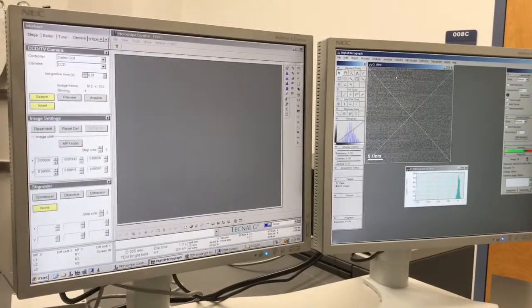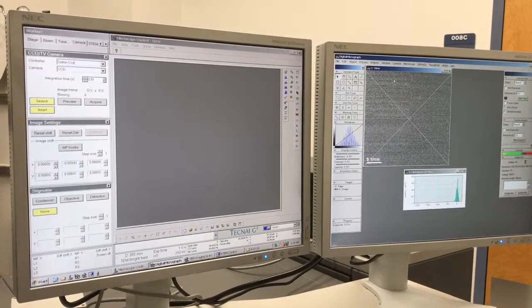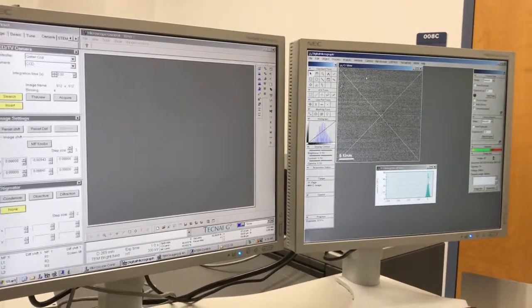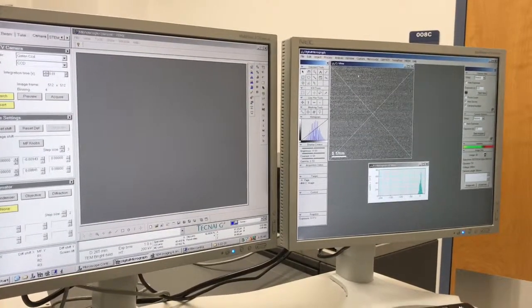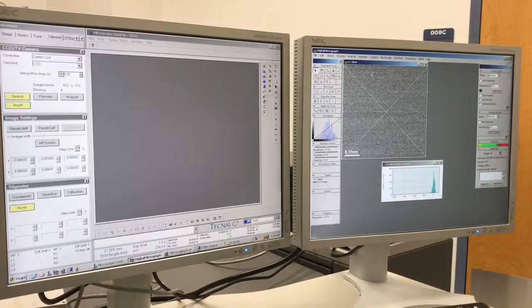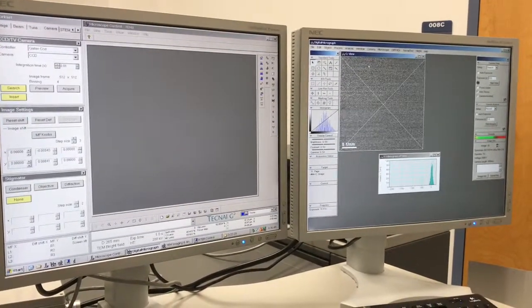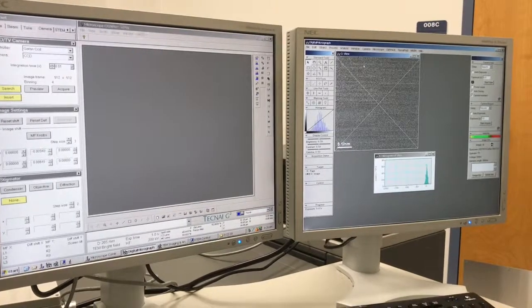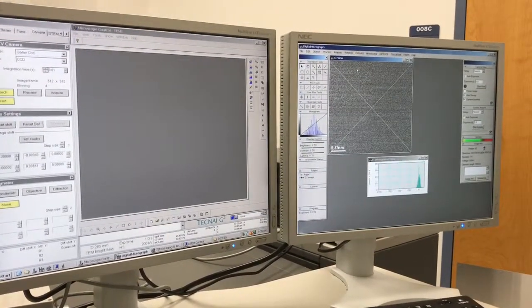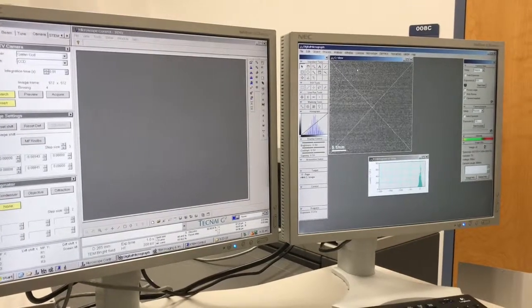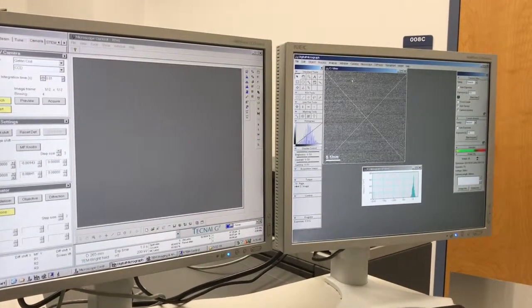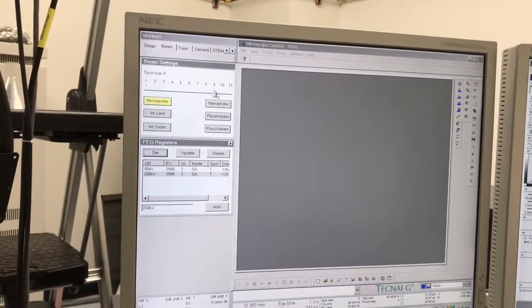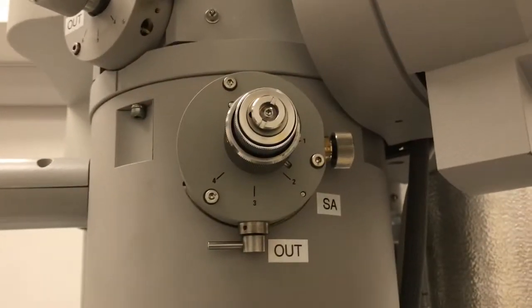Okay, so I switched specimens, and now I have a silicon single crystal specimen in. There are some additional things to discuss when working with the camera when you're recording diffraction patterns, and specifically diffraction patterns from single crystal specimens. In the video I recorded on selected area diffraction, a lot of this is review of that, but you need to make sure to use a high numerical spot size, use a selected area aperture, and we do have the beam stop inserted here.